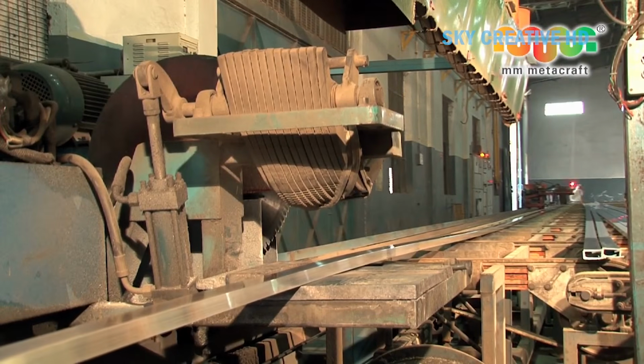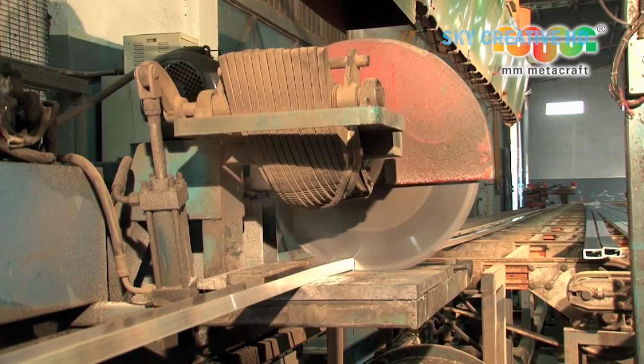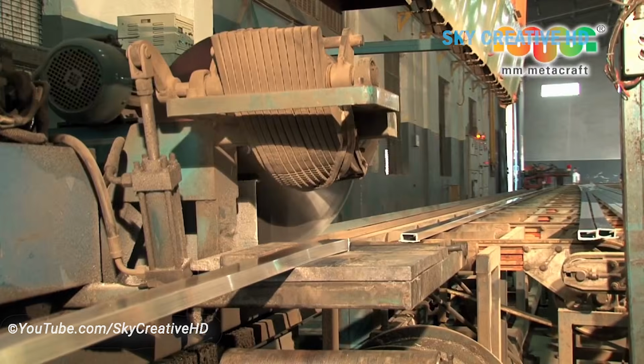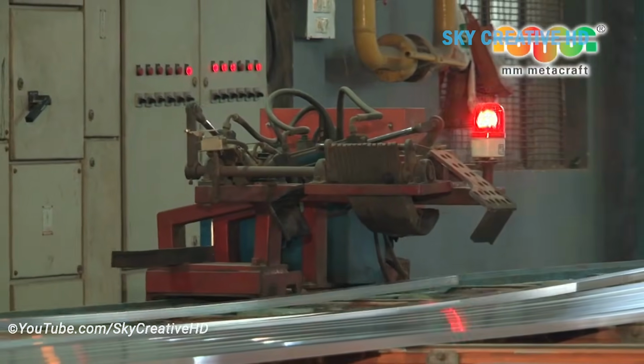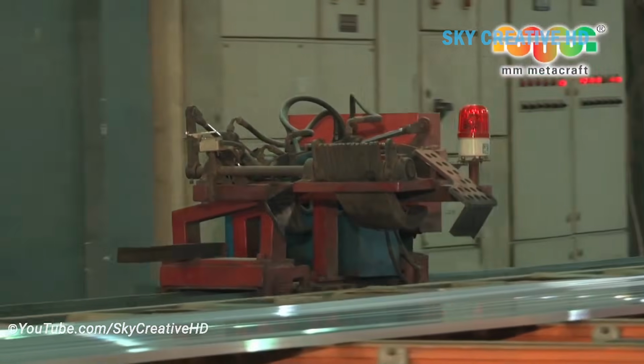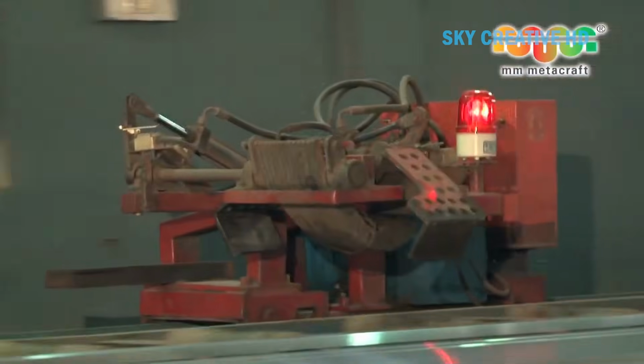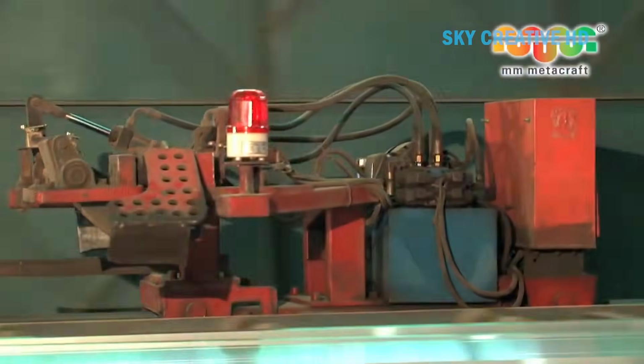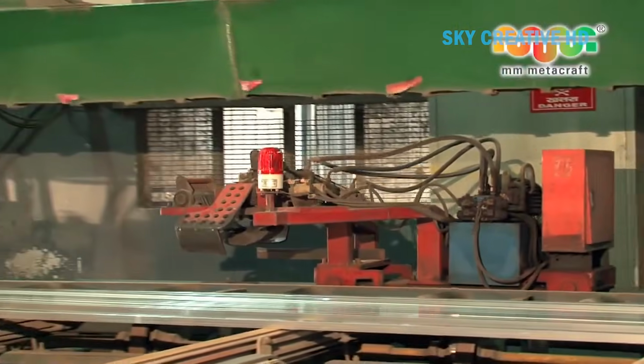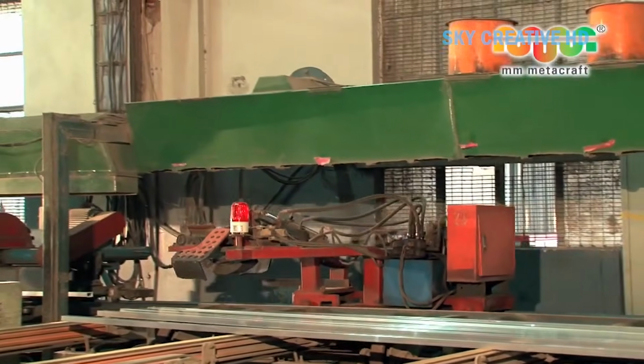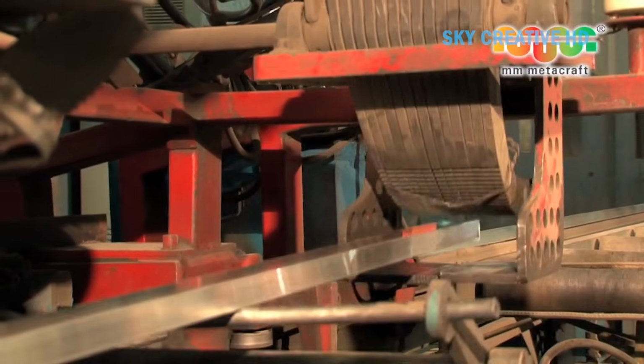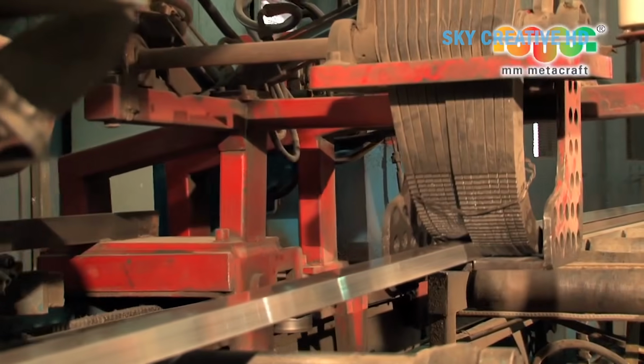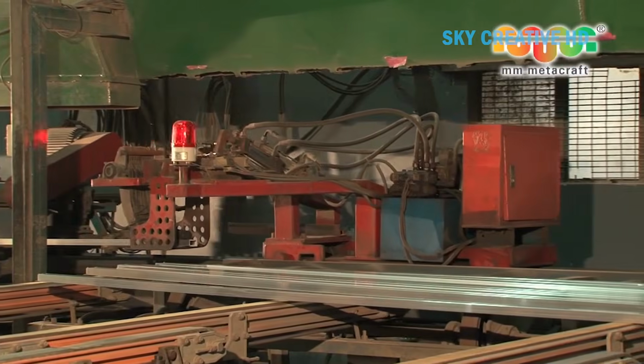At the end of the run-out table, it's quenched, cooled rapidly with air or water spray to lock in the metallurgical properties established during extrusion. Speed matters here. The time between die exit and quench affects the final temper of the alloy and its mechanical strength. After quenching, the long strands are cut to standard mill lengths, typically 20 to 25 feet, and moved to